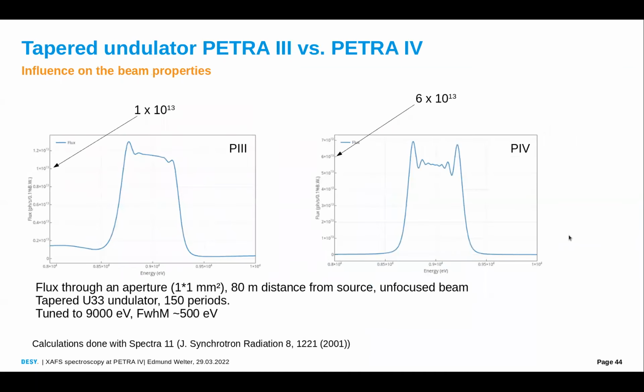And it will be worse at PETRA IV due to the smaller emittance. These oscillations become more pronounced. This is the case here for PETRA III, and this here is the case for PETRA IV calculated. These calculations seem to be more or less correct, as we have seen in the previous slide.